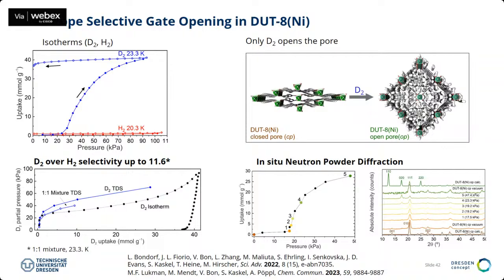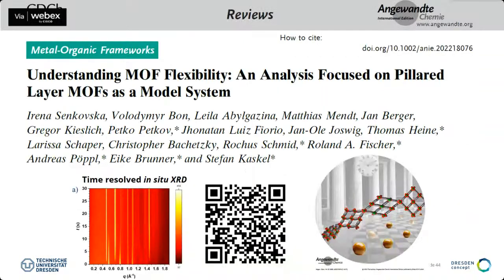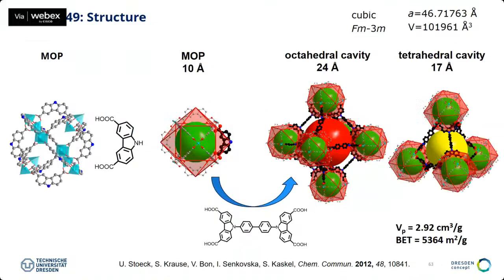And again, with the in situ methodologies, you can also analyze where the D2 molecules are inside the pores. And you can do this with neutron powder diffraction. It's very powerful. You see the different powder diffraction patterns with deuterium. You can localize the deuterium molecules and then also get an insight into the structure of the adsorbate inside the pores. So I hope I could show you that these are very interesting materials, and there are still many open questions in this class of gate-responsive, gating metal organic frameworks. If you're interested, we just published a review on these kinds of materials. And I think there are still many open questions that need to be studied.